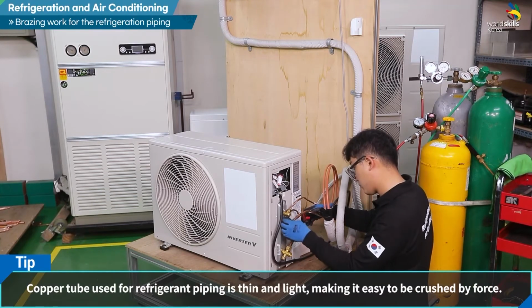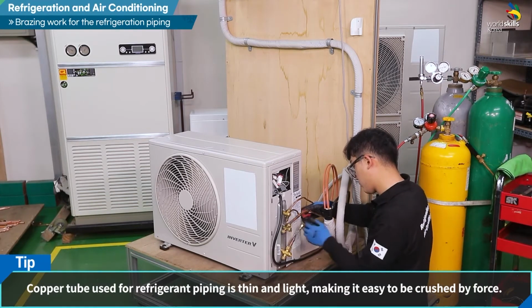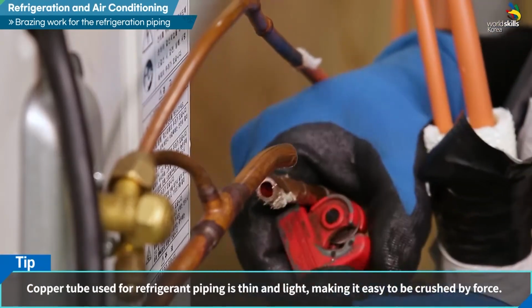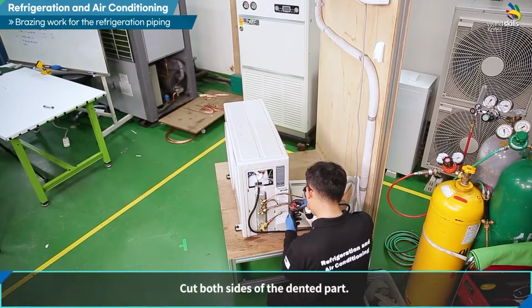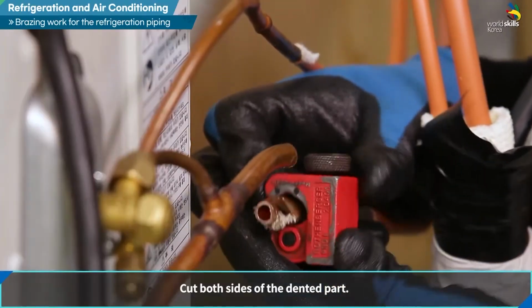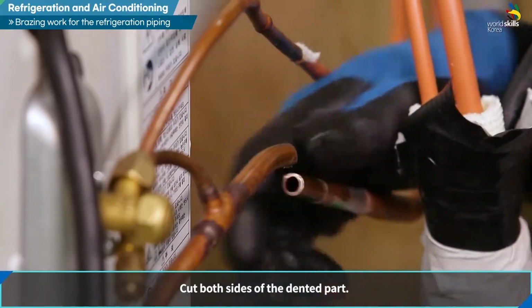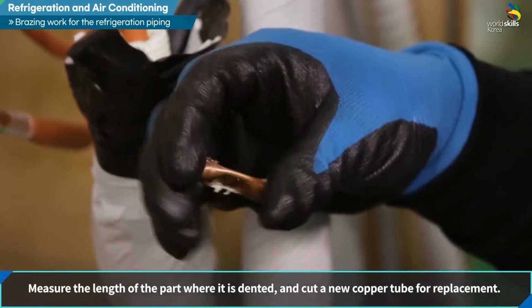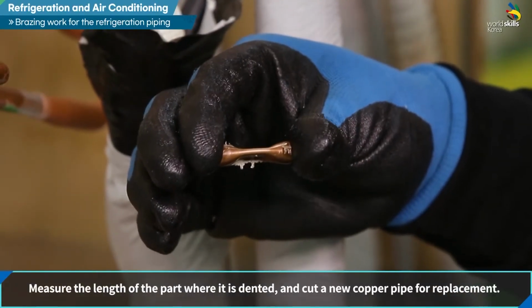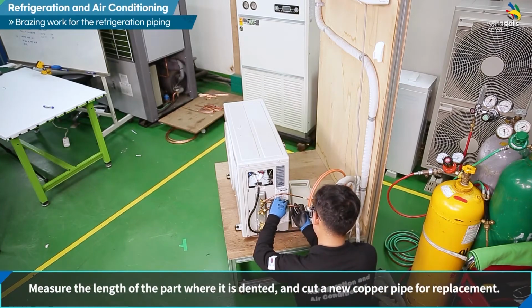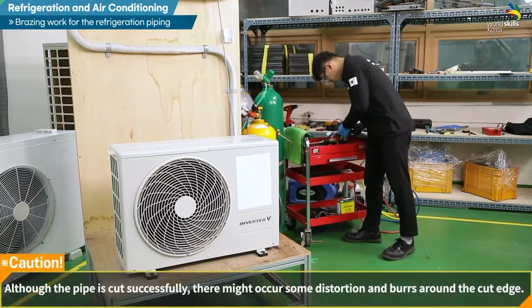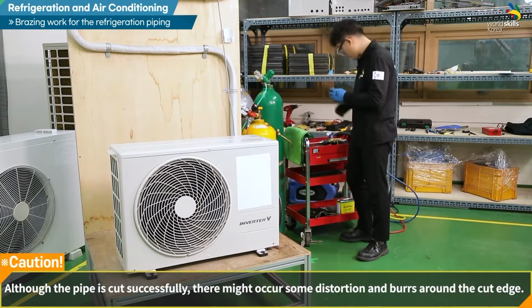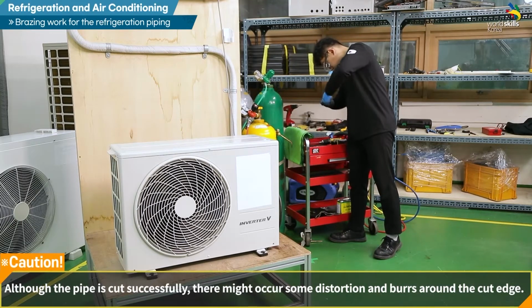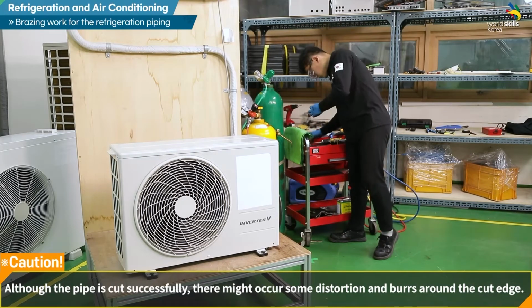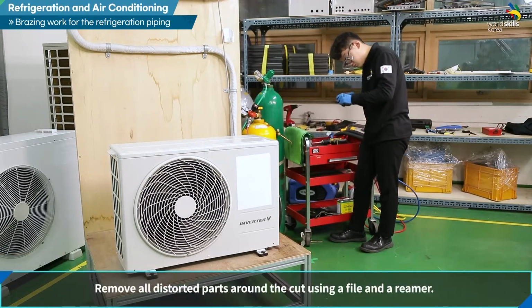Copper tube used for refrigerant piping is thin and light, making it easy to be crushed by force. Cut both sides of the dented part. Measure the length of the part where it is dented and cut a new copper tube for replacement. Although the pipe is cut successfully, there might occur some distortion and burrs around the cut edge. Remove all distorted parts around the cut using a file and a reamer.